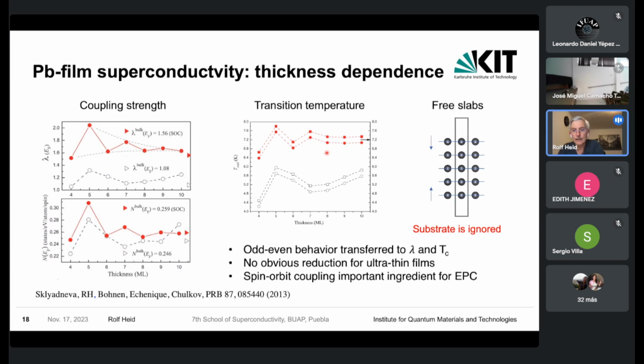And when one plugs that now into the Eliashberg gap equation, you can also extract a prediction for the transition temperature, and then you also see that this oscillatory behavior also transforms to the transition temperature as a function of the monolayer thickness. Here's actually the bulk value, so you can see that you have this oscillatory behavior, but what you don't see is a reduction of the transition temperature as seen in experiment. We believe, or I will show some arguments, that the reason for that, or at least one reason for that, is given by the way we do this calculation.